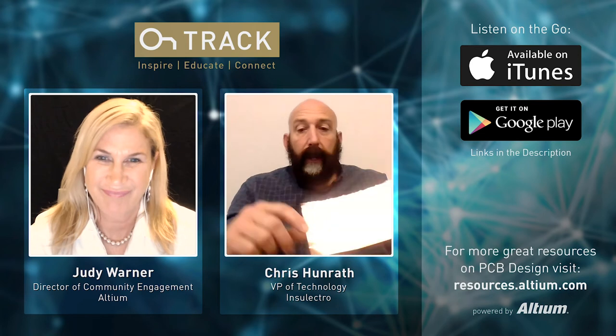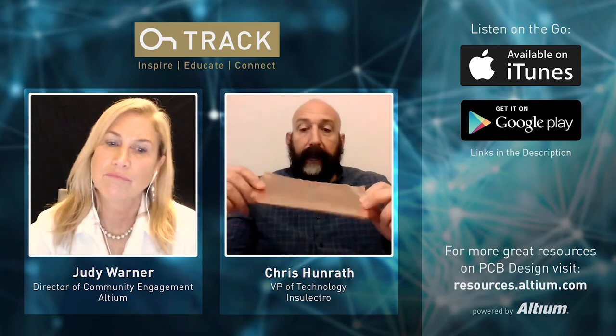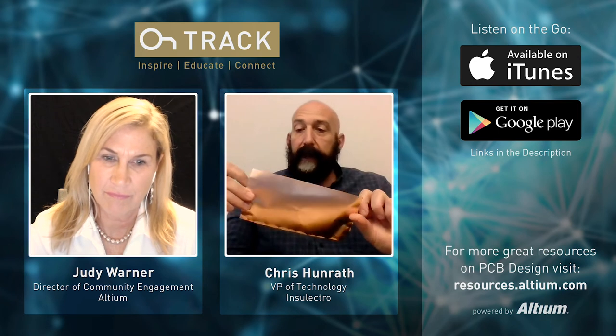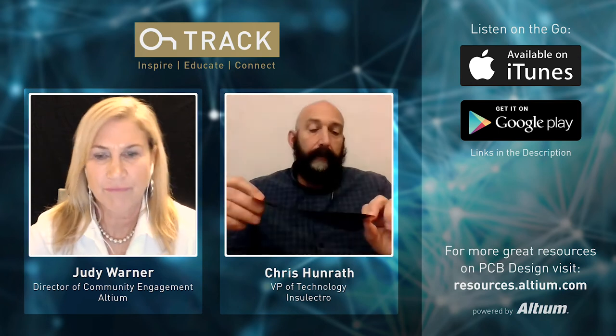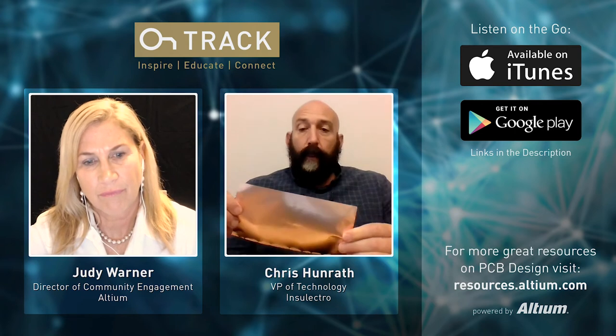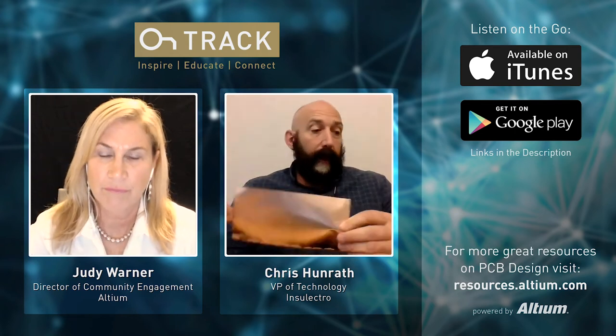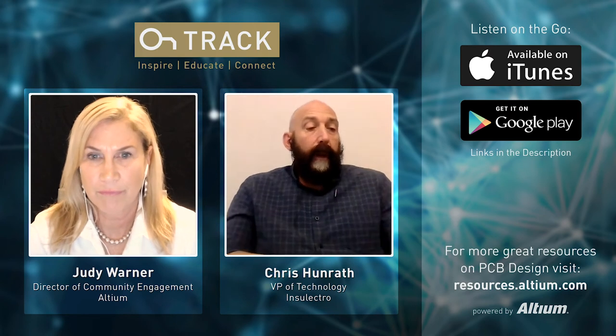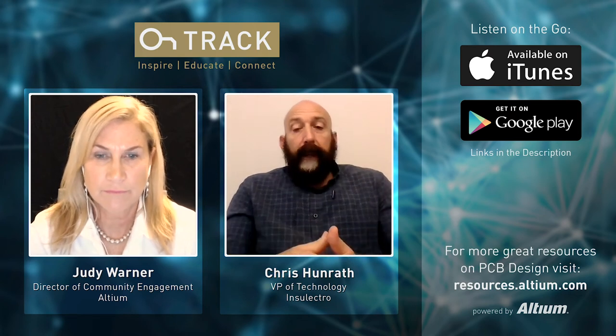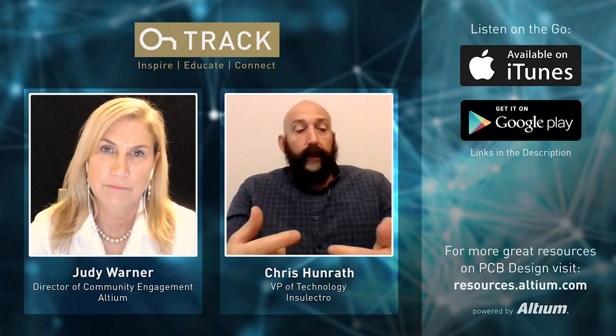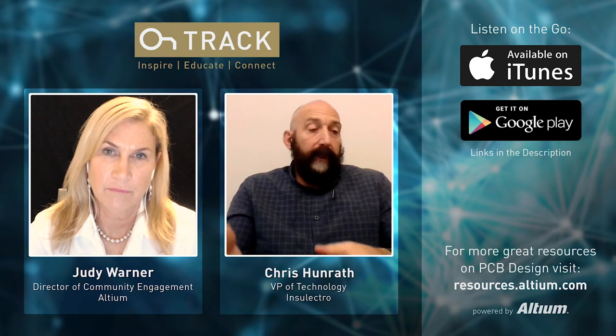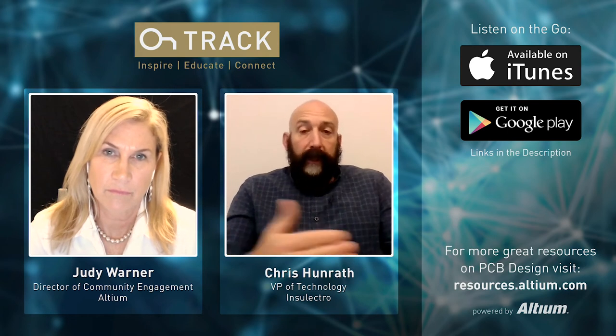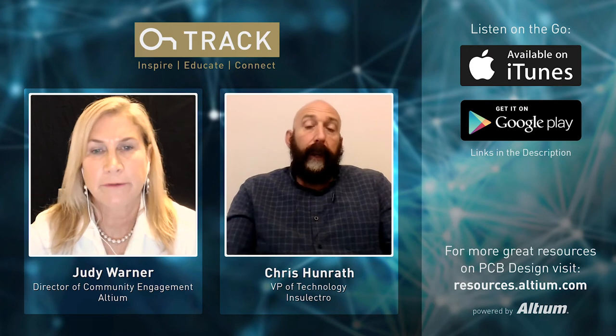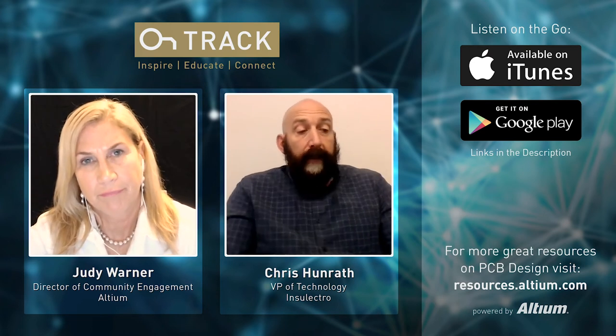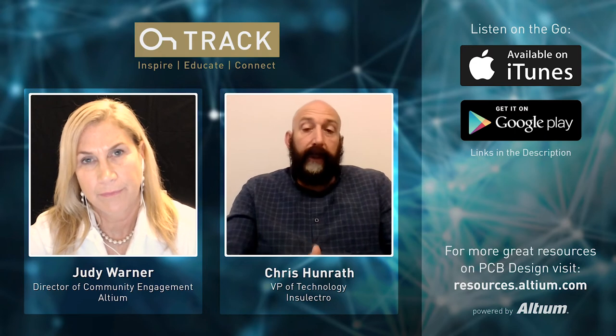Actually, I have a sample here. This is some Pyralux clad. You can't see the dielectric inside, but it's got rolled annealed copper on both sides. It used to be limited to 1/2 ounce or 18 micron and thicker. A little side note on foils: as you go thicker, it's harder to make electrodeposited foils because there's more plating time on the drum. With rolled annealed, it's the opposite. Thinner foils are harder to manufacture because you need more rolling processes to make the foil thinner and thinner. Now we can get rolled annealed copper thinner, down to 9 micron or 1/4 ounce.